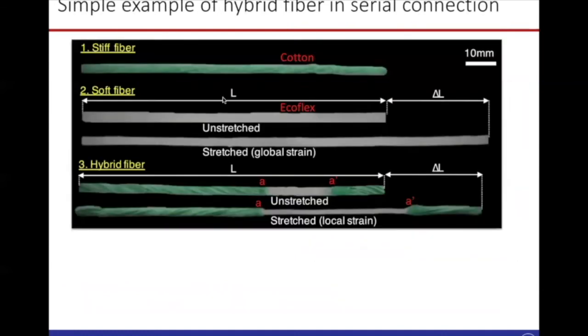So we show here a picture, a highly stiff material, which is a cotton fiber, and a soft material, which is Ecoflex. By connecting these two materials, you get a hybrid fiber. And by making this soft part softer and softer, very soft, then you can easily stretch this hybrid fiber like a stretchable material. So this soft part enables a good stretchability for the hybrid fiber.